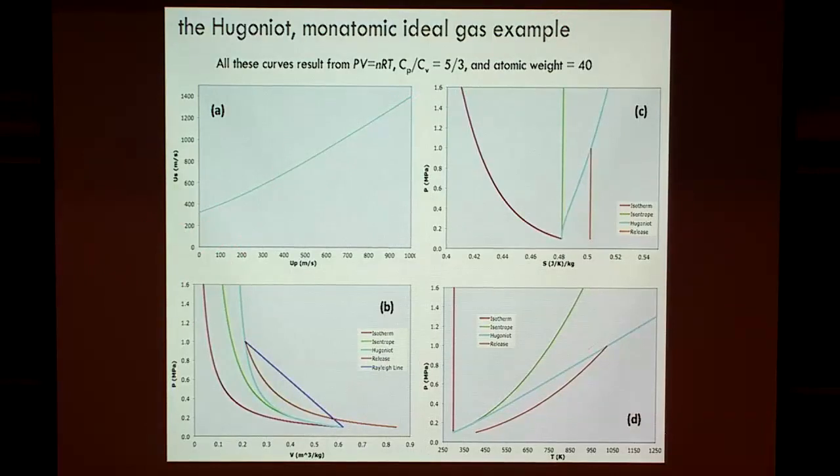So I'm confused about how you know it during an experiment. How do you know when you've reached the Hugoniot point? Because if you're just measuring the two velocities, how do you figure out when, there it is, we're at the equilibrium Hugoniot point? For a well-behaved material, the shock front is extremely sharp. It goes up the Rayleigh line in about 1 nanosecond or less, right? And so I don't really have to know. I can observe and wait till I see steady behavior. And usually there's not much waiting involved.